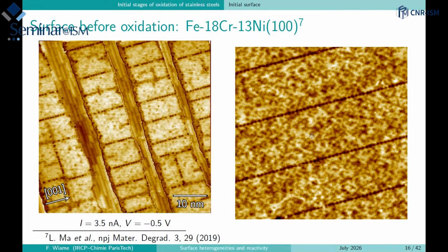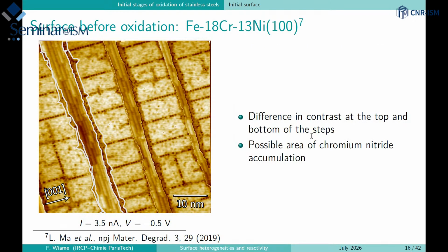If we look now at the homogeneity of the composition, you can see that in fact we have, as we have said, different heterogeneities of chemical nature. In fact, we can also see that at some places on the surface, typically at the top and the bottom of the step edge, we have a change in contrast, which is associated with a change in the chemical nature of the surface, and which is in fact corresponding to the area of chromium nitride accumulation. If we calculate the amount of chromium nitride that we have at this position, this is consistent with the amount that we see by spectroscopy measurement.